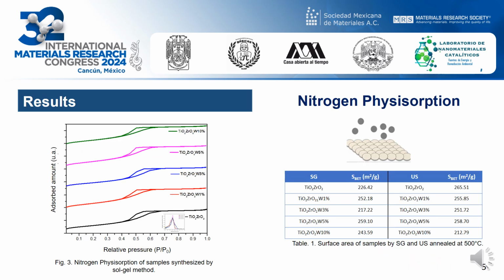On the other hand, physisorption analysis exhibits mesoporous materials with type 4 isotherm and hysteresis loop, and surface areas with values between 226 and 243 square meters per gram for sol-gel and from 255 to 212 square meters per gram for the sonochemical method. The pore volume distribution exhibits a unimodal behavior in both methods.